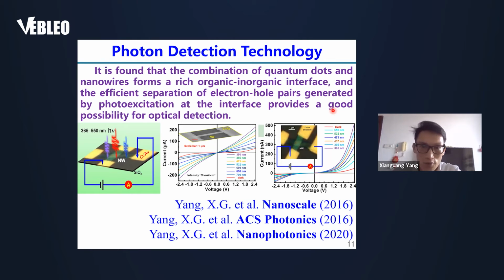After photon emission and photon transmission, we go to photon detection technology. This is very interesting. It is found that the combination of quantum dots and nanowire forms rich organic and inorganic interfaces, and the efficient separation of electron-hole pairs generated by photon excitation at the interface provides a good possibility for optical detection. You can see we got UV and visible detectors. And this is the schematics.